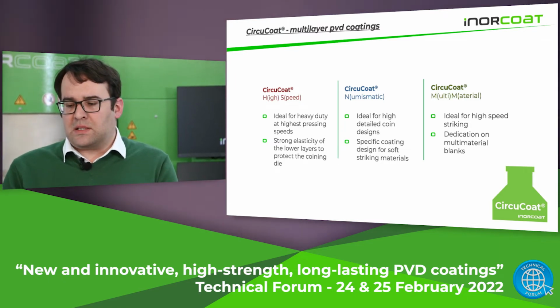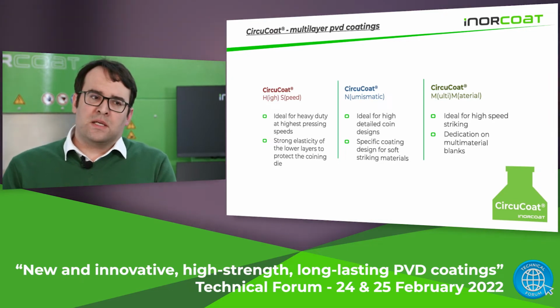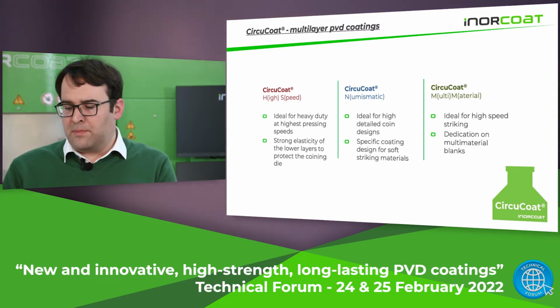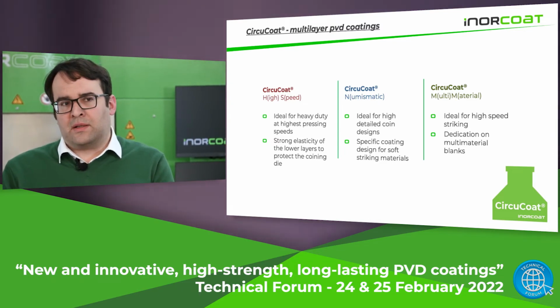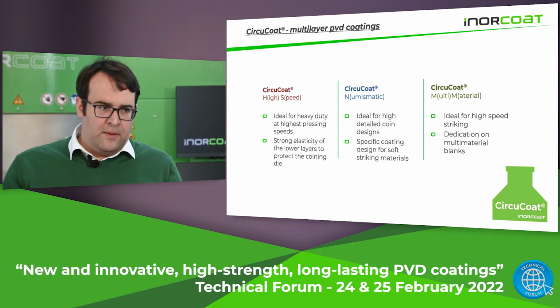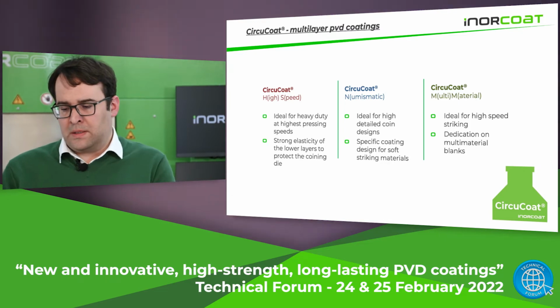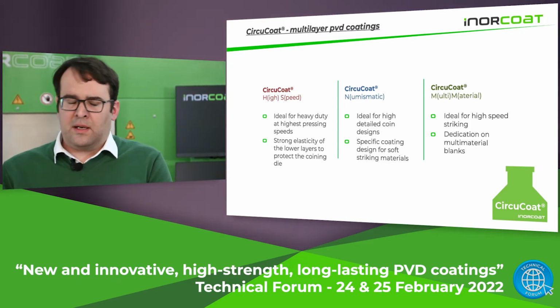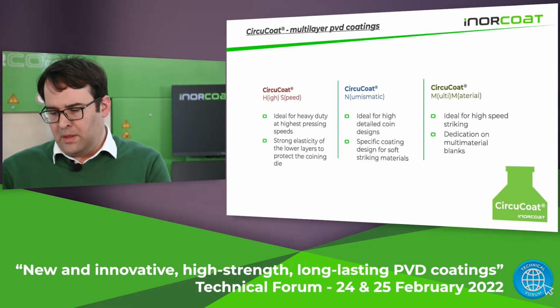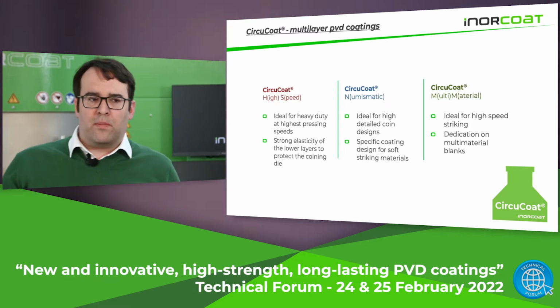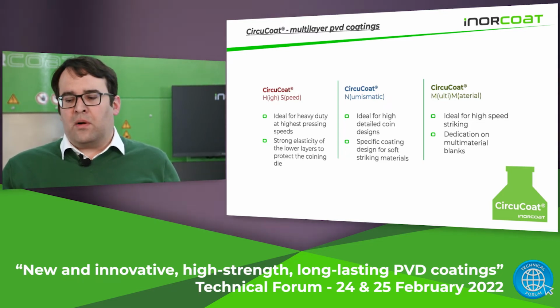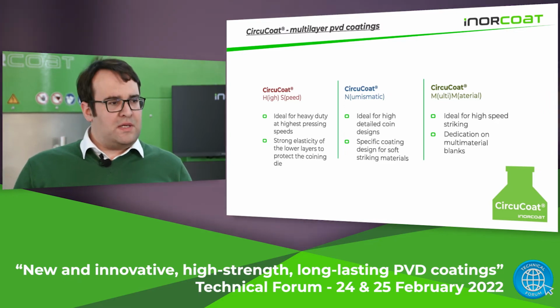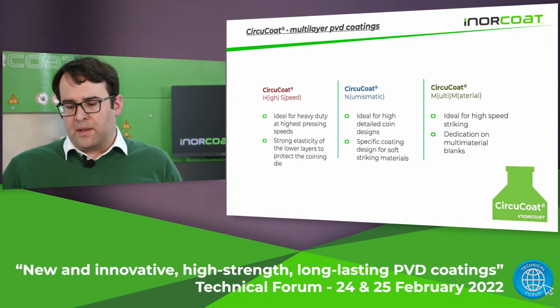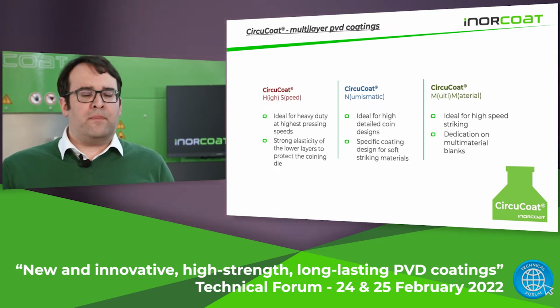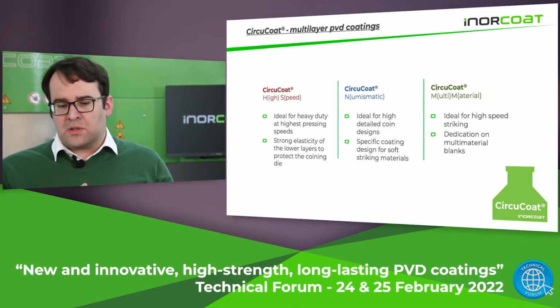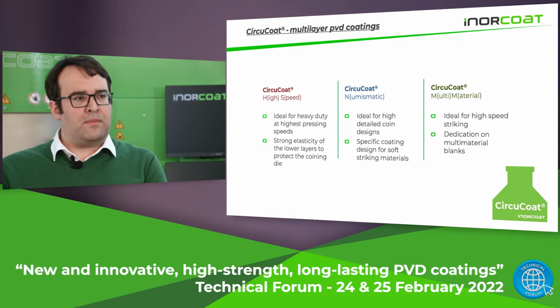And the last one is CircuCoat MM. CircuCoat MM has been developed for multi-material, so bicolor blanks, which have different materials in the coin, like, for example, plastic substrates or a standard bimetal blanks, which we know from the €1 and €2 coin. The specificity of our coating is that they are all based on the same elements, but each coating recipe has some specific characterization independent of what we want to strike, which give us a very high flexibility and which also helps us to find the optimal coating solution for the dependent blank material which we want to strike.